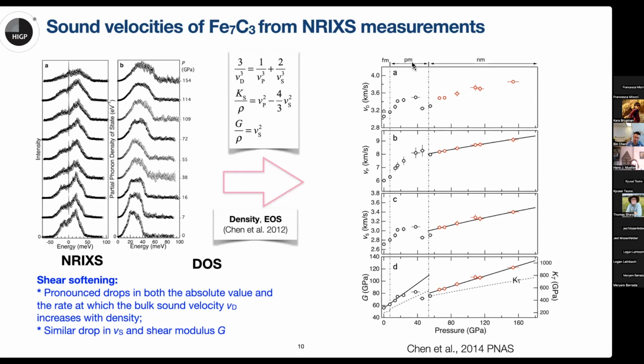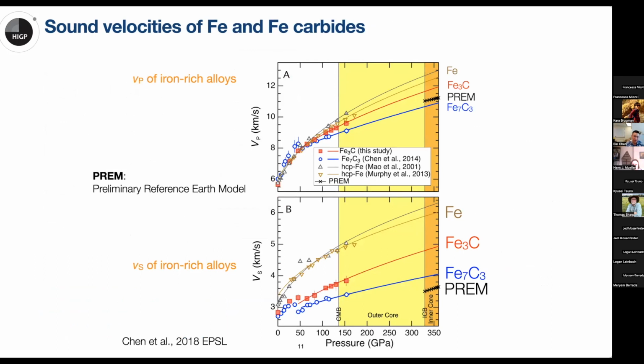And this corresponds to the paramagnetic to non-magnetic transition, which has been confirmed by our X-ray emission experiment. So this is the high spin to low spin transition for iron. We extrapolate our data to the Earth's inner core conditions based on Birch's law. So we can see that by alloying iron with carbon to form iron carbide phases, it can reduce the compressional wave velocity and the shear wave velocity of iron, bringing it closer to the seismically observed values.